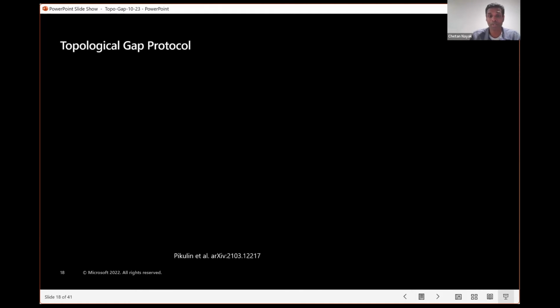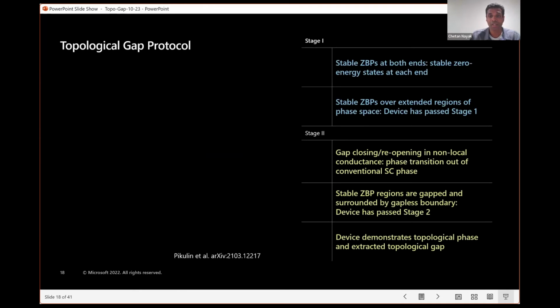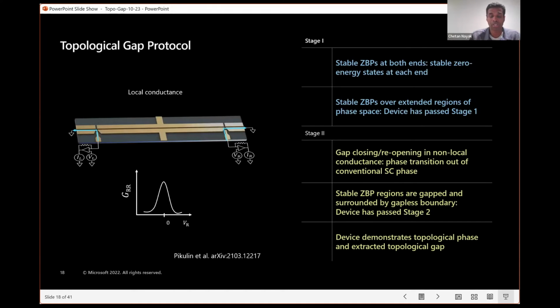So we introduced this topological gap protocol to do just that. What the protocol does is it comes in 2 stages, and it does 2 things. First, it looks at the local conductances, and it looks for a zero bias peak in the local conductance. So we take the derivative of I right with respect to V right, and the derivative of I left with respect to V left. Those are dominated by a current that flows into the device here and then goes off this way, or flows into the device here and then goes off this way, depending on whether it's GRR or GLL.